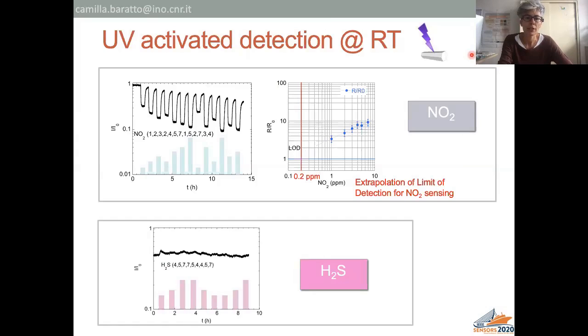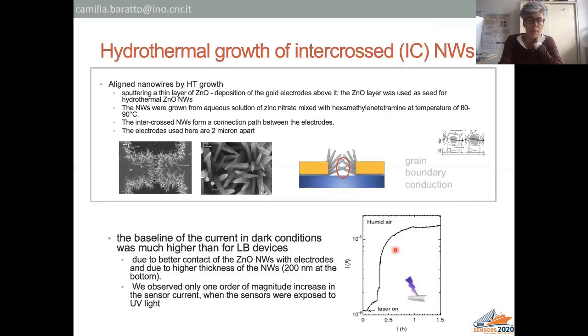We tested different NO2 concentrations, and from the calibration curve reported here, we can extrapolate the limit of detection, which is 0.2 for NO2 sensing, which is the attention level for NO2 detection outside. H2S detection was not reached at room temperature with UV activation, probably due to the lack of energy to activate the reaction.